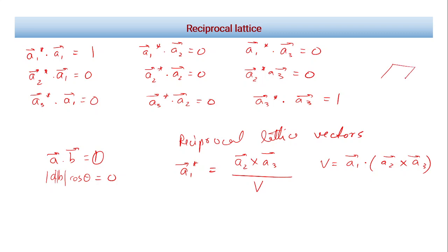So if I have a unit cell in real space, with A1, A2 and A3, then A2 cross A3 is the area of the base of the unit cell, and when I take the dot product with A1, it gives this whole volume. So it is the volume of the unit cell in direct space. Sometimes there is also a multiplication of 2 pi, so with or without it, it's fine. We will discuss that later, but even without it, that's okay. The things won't change.